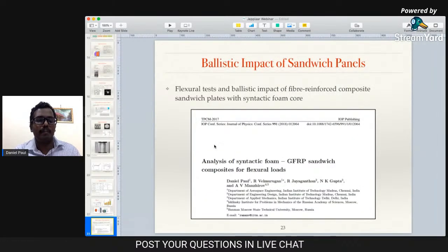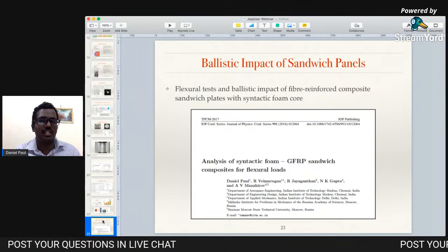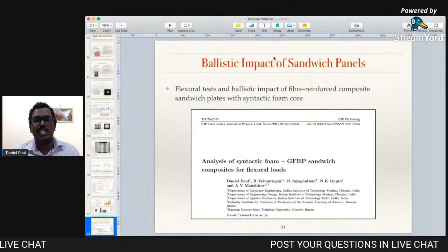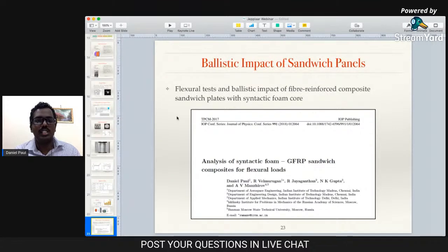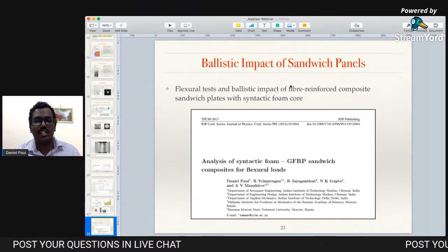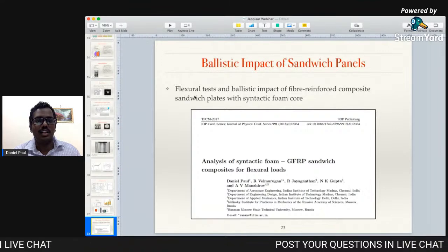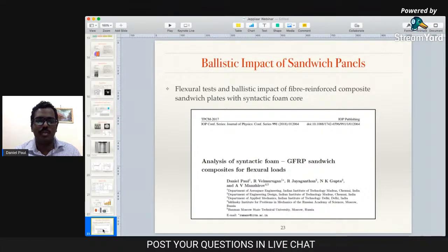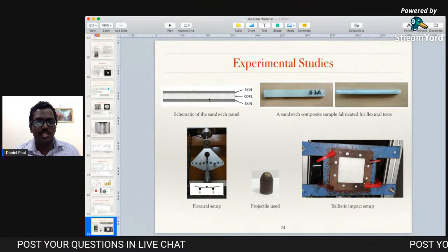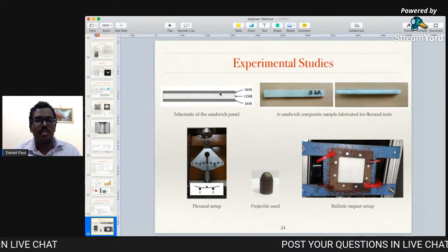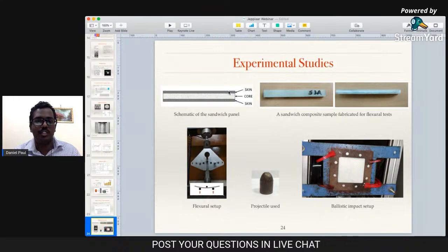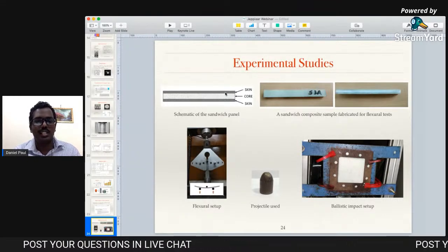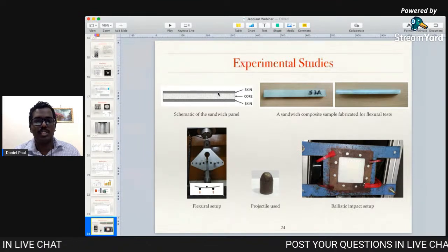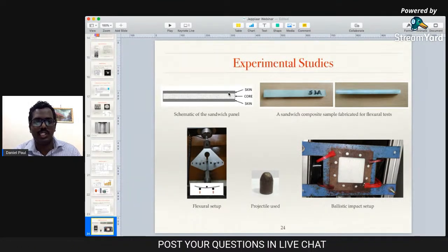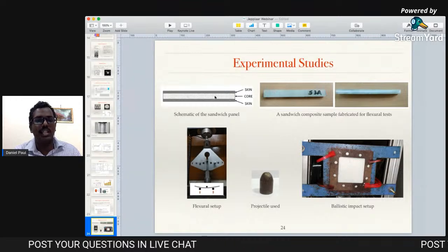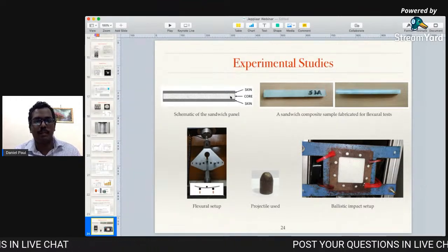Another brief thing that I would like to say is the second part of our research, which is the ballistic impact of sandwich panels. In this, we tested some sandwich panels containing the core material, which is made up of these syntactic foams, and the skin, which is made up of normal GFRP, or glass fiber reinforced polymer composites. The skin had bidirectional glass fibers and commercially available epoxy, while the core was made of epoxy and hollow glass particles, as we saw earlier.